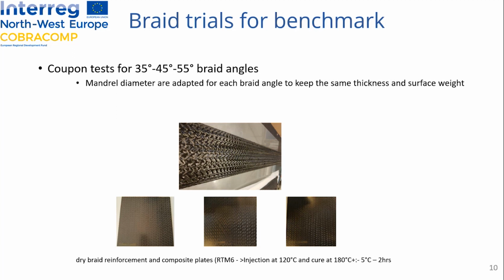After several meetings between us to discuss the minimum UD ratio or the maximum braid thickness we can achieve for multi-layer interlock braids or monolayer triaxial braids, some braiding parameters are fixed. We fixed 3 braid angles: 35, 45, and 55 degrees. And Eurocarbon and CENTEXBEL have to adapt the size of the mandrel to keep the thickness and the surface weight constant, to compare the future composite plates. The braids are done on a circular mandrel to obtain a homogeneous yarn placement, and they were cut to be used in a flat direction and injected by co-expert partners.